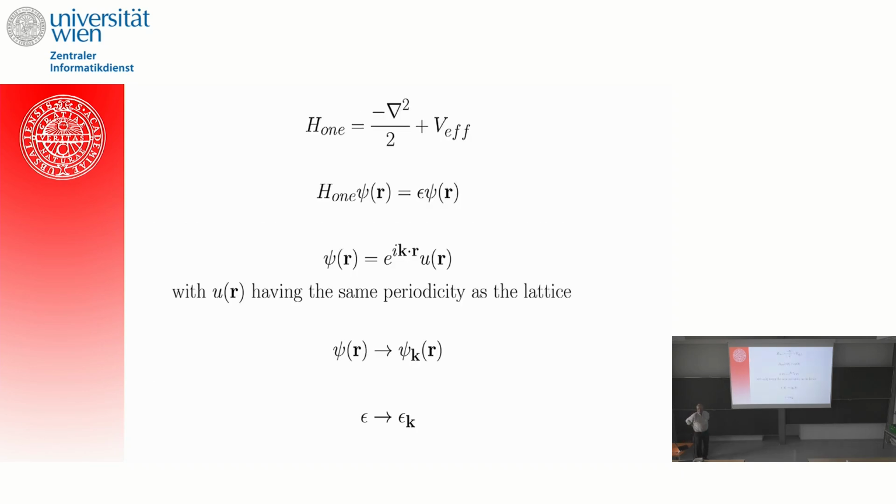So starting from the very beginning, this is how density functional theory tells us a way to calculate the many-body problem without actually solving a many-body problem. We translate it into an effective one-electron problem. So here it is, the famous Kohn-Sham equation. All the many-body effects that the solid has are baked into this effective potential, and then the trick is to find the best possible one.